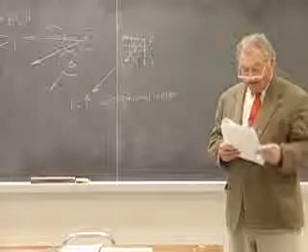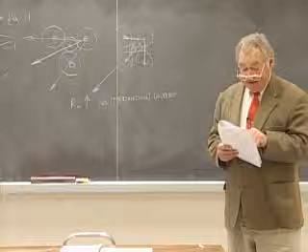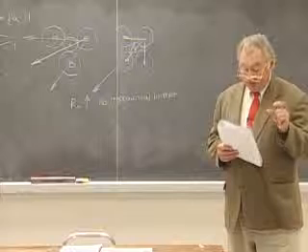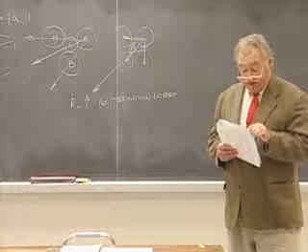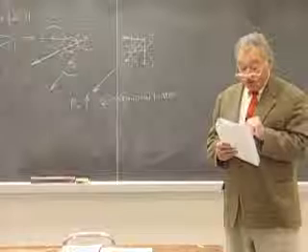So the third column in the Shannon and Prewitt tables is coordination number. And if you look at several ions, there, for example, barium has 6 coordination, 7 coordination, 8, 9, 10, and even 12. And as you go down that list of radii, it gets larger as the coordination goes up. And it's a relatively small effect. It's on the order of 5 or so percent, but still, when trying to calculate an interionic distance, you should use the radius that is appropriate for the coordination numbers.